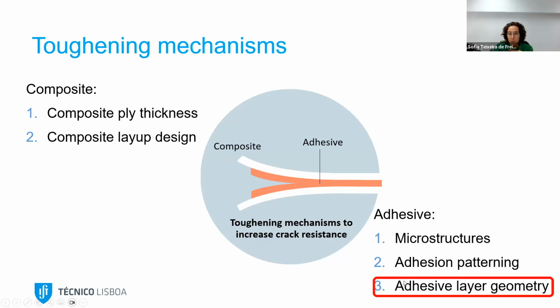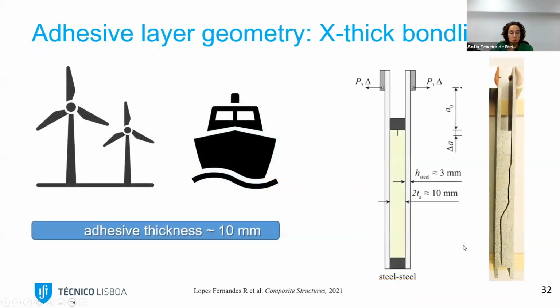And finally, the adhesive layer geometry. So what can we do in the geometry of the adhesive to create toughening mechanisms? And this was a work that was performed for very thick bond lines for the shipbuilding industry or for wind turbine blades. In these industries, we have quite thick bond lines. So in aerospace, we have about maximum 1 millimeter. Here we are talking about 1 order of magnitude higher, 1 centimeter or even further. So here you see the same type of test, the double cantilever beam, in which we open a part, but now with the 10 millimeter thick bond line.